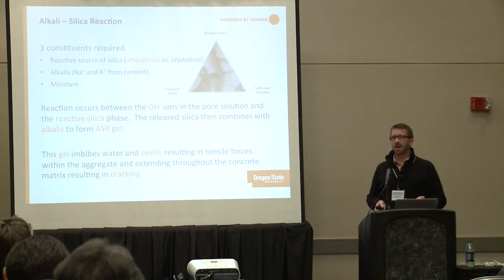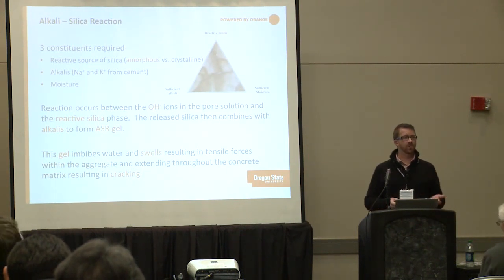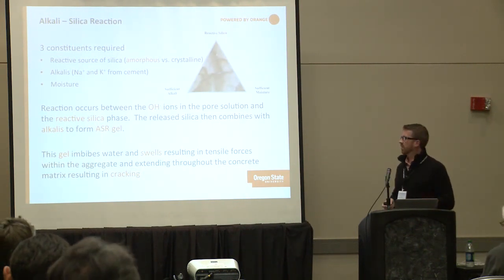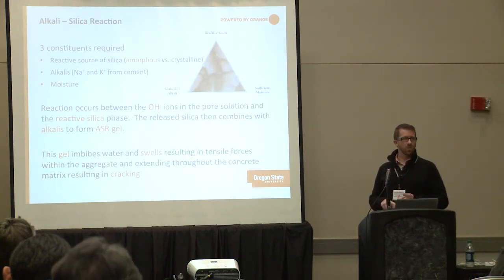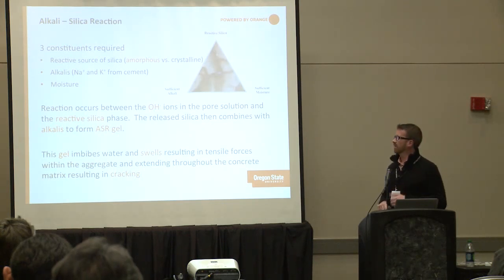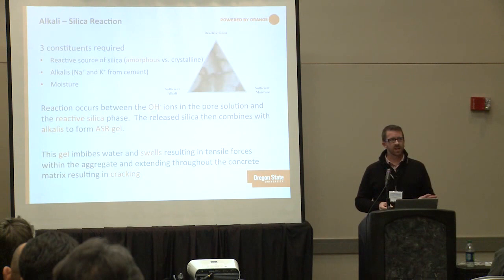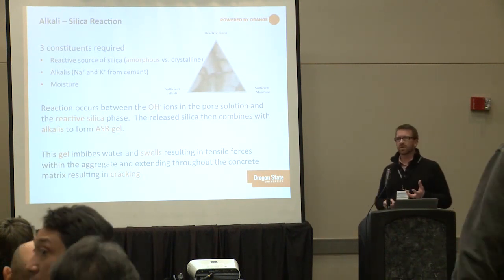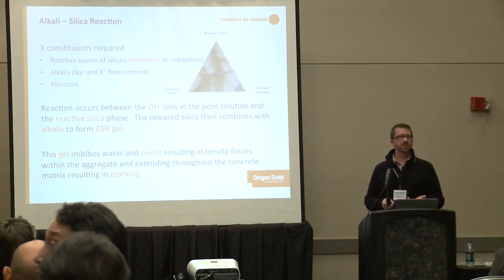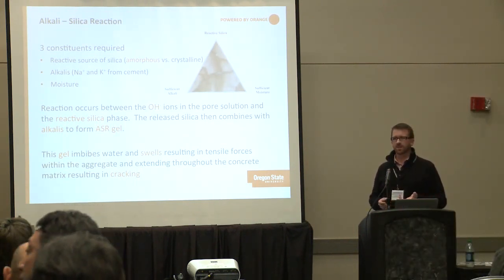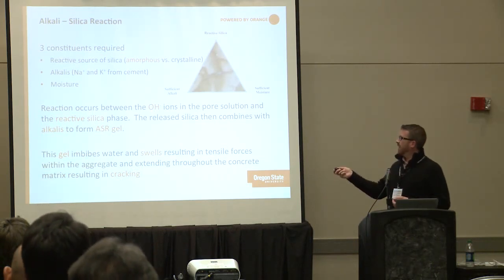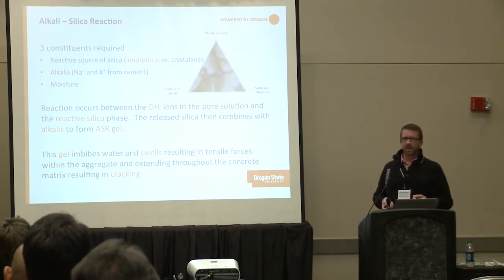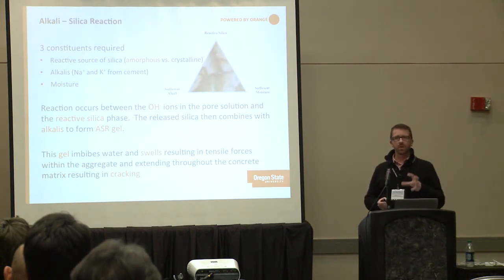If you don't want ASR in your concrete mixture, you have to eliminate one of these three factors. If that's not an option, you have to look at other ways to mitigate or limit the reaction — things like supplementary cementitious materials, chemical admixtures, or aggregate beneficiation. The pore solution inside concrete has a very high pH, around 13 to 14, similar to drain cleaner. It's this high pH and the presence of hydroxyl ions that react with reactive silica in the aggregate to form a gel.